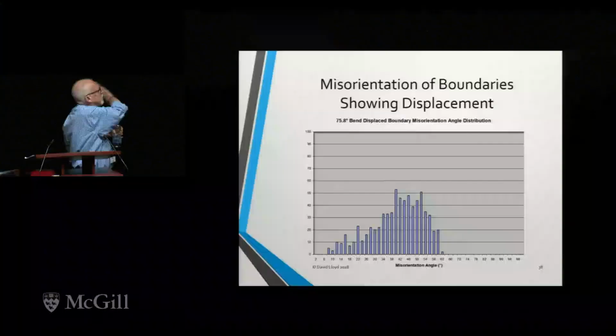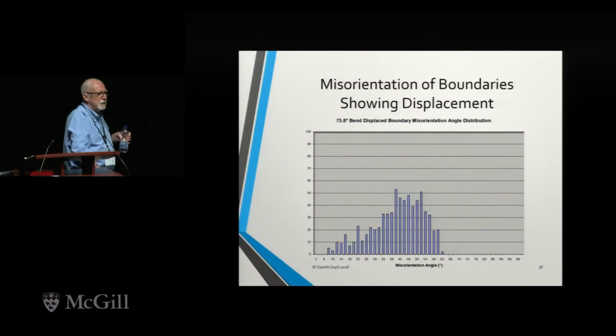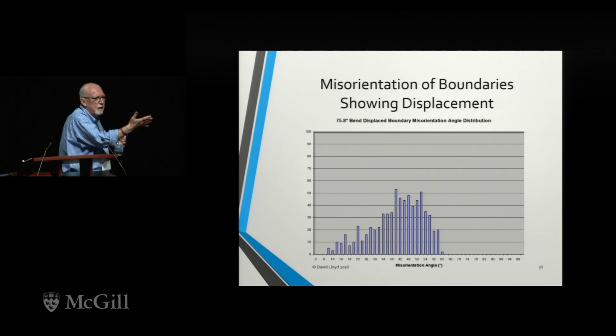And then you can do the misorientations across the boundary. What you find is that the boundary misorientation is totally irrelevant to what you see. There are no special boundaries there that are giving rise to this. And Tony Rollett, essentially on tensile samples, much lower strains and lower extents, and found essentially the same thing.